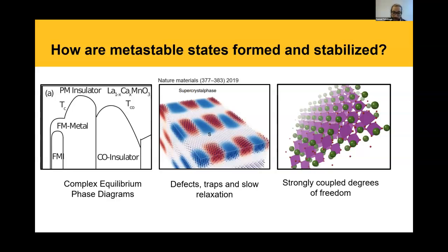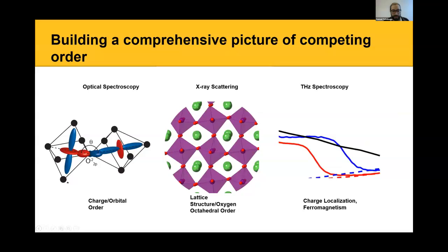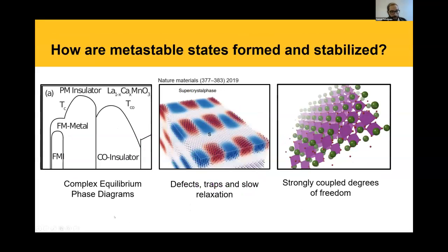What these systems seem to have in common is, first, complex equilibrium phase diagrams. There seems to be a need for some kind of competing order in the system. In other words, different kinds of order, whether these be different kinds of charge density wave orders, or in this case charge order and ferromagnetism, or in the vortex supercrystal phase that's been led by Vladimir Stoica, the different kinds of ferroelectric ordering. The vortex supercrystal phase is also a good example of one of the other key ingredients here, which is the formation of defects and traps and slow relaxation.